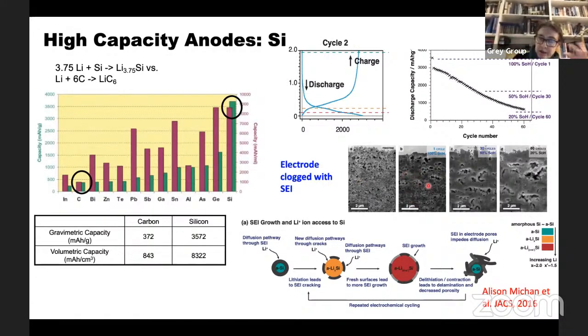But then as you react further, you get this electrolyte decomposition, and you just basically get this mushy mess of decomposed products. And by the time you've cycled 60 times, you can see it's just become this dense mat. And the capacity, so we measure the capacity in milliamp hours per gram. So amp time, so current times the time we do it for. So that's the amount of energy density per unit of gram. And you can see it's dropping significantly over only 60 cycles. And that's just literally the resistance of getting the lithium ions through this junk.